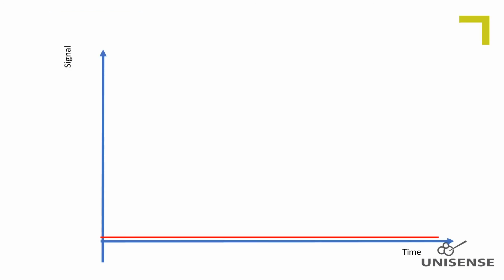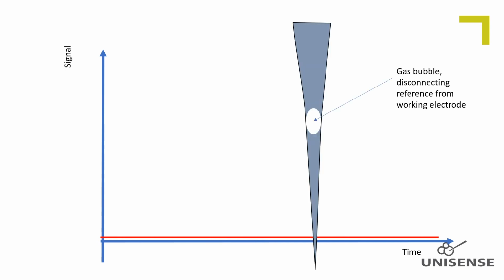I showed before how the signal progresses during the pre-activation phase. If there is no signal rise when polarization is turned up to 1.3 volt or minus 1.3 volt, but instead stays close to zero, it might be due to a gas bubble stuck in the tip, which disconnects the working electrode from the reference.